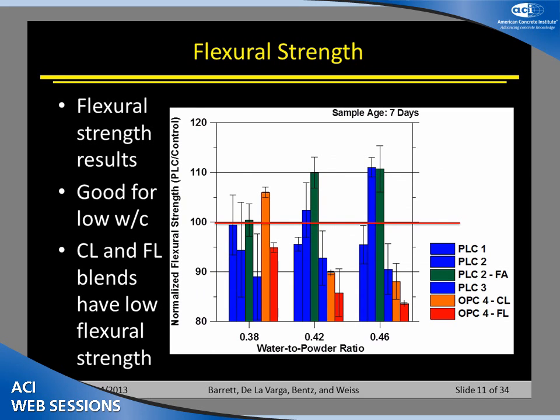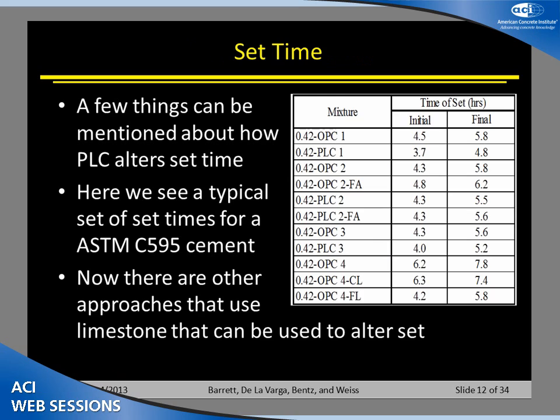Flexural strength, again, with the commercial systems, the conventional PLCs shown here in blue, PLC with fly ash shown here in green. We see very similar performances. We can start to get down a little bit lower on one particular clinker, but in general, the performance is very similar. Again, the orange and the red show the effect of dilution when you're just adding the limestone into the system and not taking advantage of those finer particles.